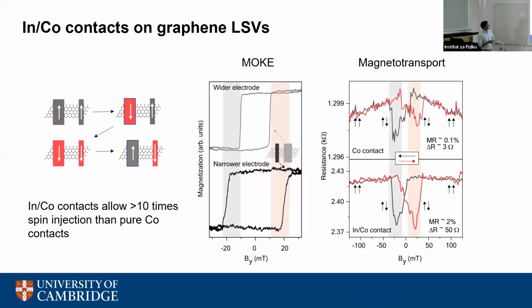What do we do for magnetotransport? First of all, we do MOKE to measure the magnetic hysteresis loops of these devices, and we see square hysteresis loops for our electrodes, which is governed by the shape anisotropy of the magnets. And you can do magnetotransport. This is the magnetic field versus the resistance. With pure cobalt, we just see a change of around 3 ohms, which is very little. But with indium cobalt, you can see a change of around 50 ohms. This high spin injection is enabled, and this increase is determined by the amount of spin injection. And this is due to the fact that now we have a tunnel barrier due to this van der Waals interface between the metal and the semiconductor.